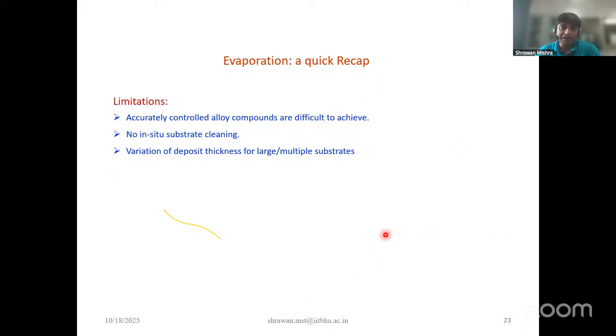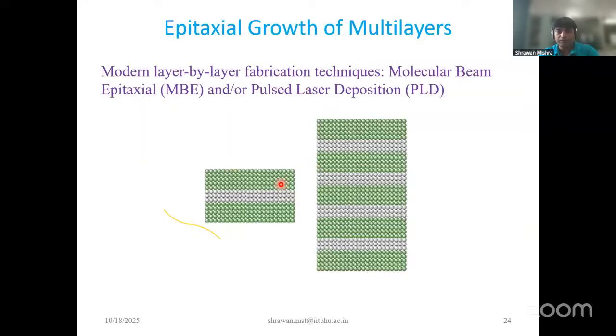Quickly, we can recap this physical evaporation based method. It has some limitations, such as accurately controlling alloys and compounds being difficult, because if you have a light element, like lithium or oxygen, controlling their stoichiometry is always a challenging task. So that's not a very feasible method for that. Also, you have no means to do in situ cleaning of the substrate to have a very clean sample. And if you don't have expertise, varying the deposition thickness is also not very easy. Using this method, you have the possibility to do stacking of material. That's what has been shown.